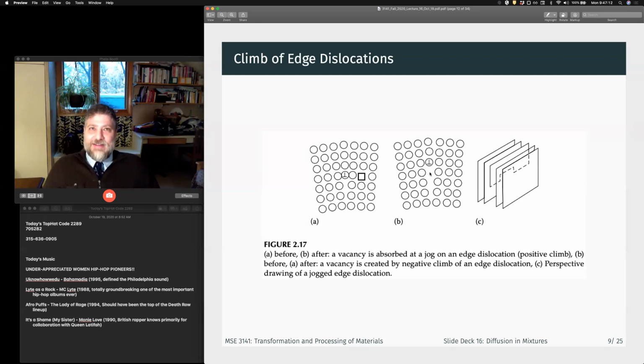I thought it was different units, but yeah. So that's if I have a 3 foot by 3 foot by 3 foot block of iron, approximately, right? Because some people are not used to thinking in meters yet. That means that the total dislocation line length is about the distance from the Earth to the sun.